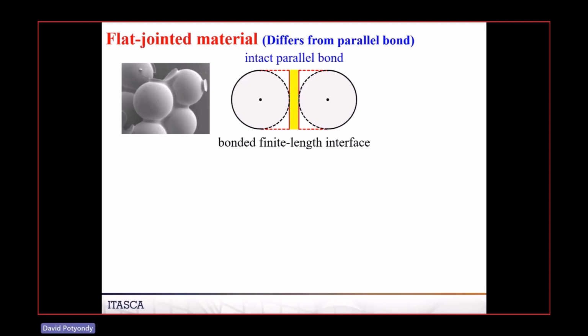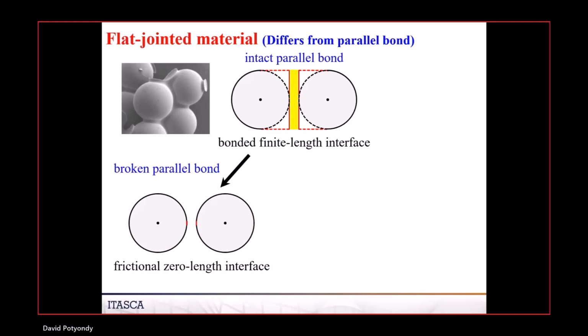And here's the thinking behind it. So this would be two discs joined by a parallel bond, where the cement is drawn as yellow. That behaves as though it was an interface between those two discs, and it's elastic. As long as the bond is present, it really behaves like that, so it has this good interlock. But as soon as it breaks, the cement is removed, and the only thing you have now is friction acting over that small area to try to maintain interlock, and that hardly provides any interlock.